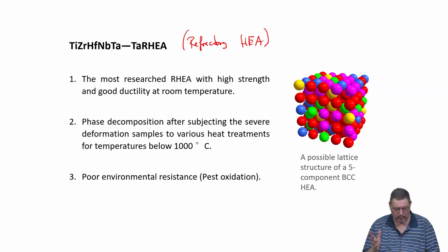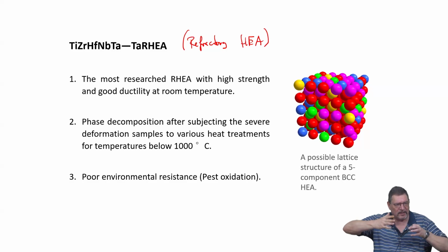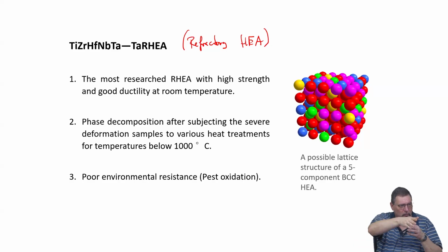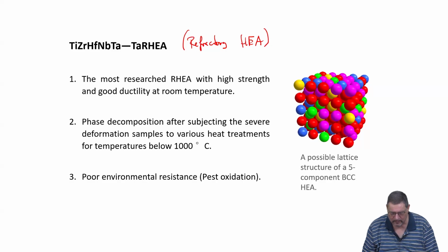And this is probably related also to stress corrosion cracking, right? So you basically build up an oxide that has a different specific volume, so it expands, and that opens a crack, and it opens, unfortunately, a crack along the grain boundary. Oxygen can move along the crack very fast, form new oxides, and so it's a self-accelerating process leading to complete and catastrophic failure. So that's bad.